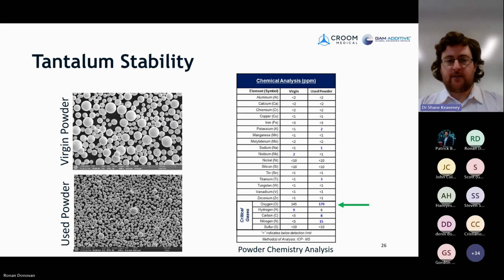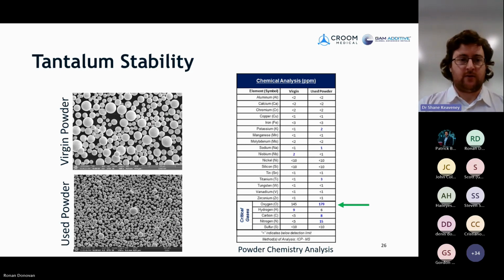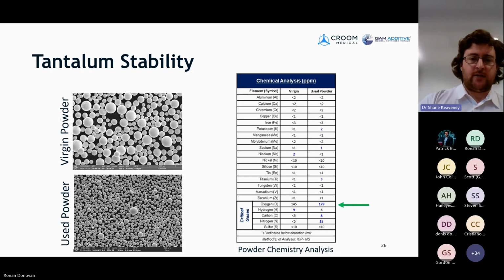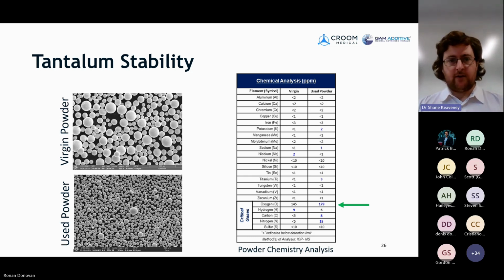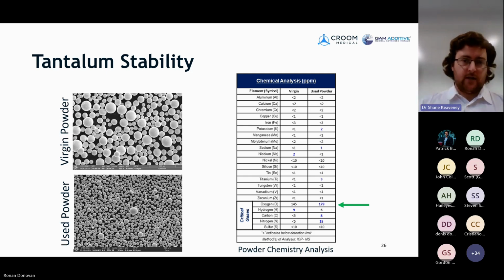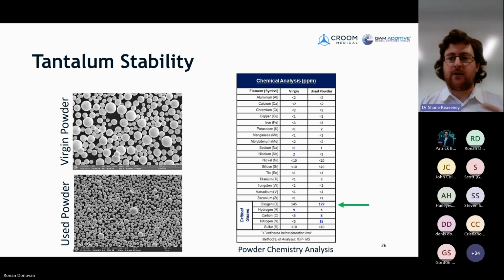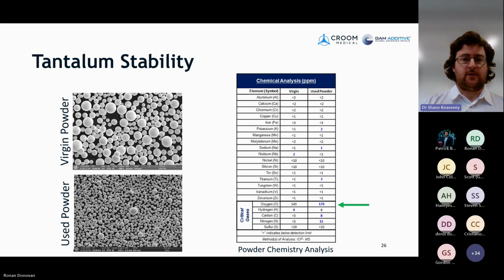In terms of the powder, which is, again, like I said, a very key piece of this powder bed fusion processes, it's always very, very important. And we've seen good consistency here. We've seen some changes between our virgin powder and used powder, but nothing detrimental. And we've seen quite a stable process as well in terms of the oxygen pickup in particular, which we can see here. Virgin, we've started with 145 parts per million. And this is after used powder. I think this is, forget the number of runs here, but quite a number of runs. We have a very low amount of pickup, so we've only picked up 34 parts per million. Now remember, that's parts per million of oxygen, so very, very stable, which we're quite happy about. And in terms of, again, the PSD, we've not seen major shifts. And in terms of the process and condensates, again, visually, we don't see a large amount of condensate, but again, in the chemistry testing, we don't see large changes here, so that's quite positive for the process.